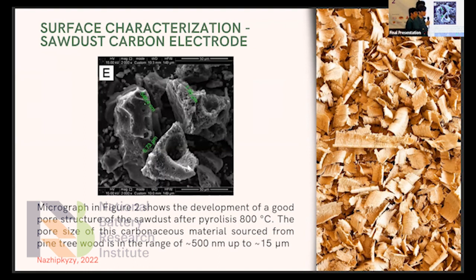So what's the method you measure? Do you use the BET to measure the porosity as well as the surface area? Okay. So we combine the actual research to fabricate the carbon electrodes and also the literature studies that we show here. Because we have certain limitations to use the scanning electron microscope in our campus, we cannot obtain the actual data from our carbon electrodes.